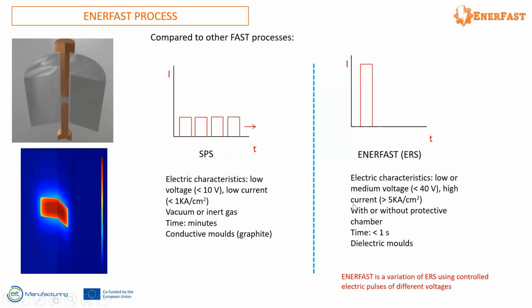In our case, we apply higher currents in a very short time, and using a dielectric die. What this means is that we put electricity only through the powder, not through the die. And for that reason, it's possible to avoid the protective atmosphere that normally is expensive in this kind of processing.